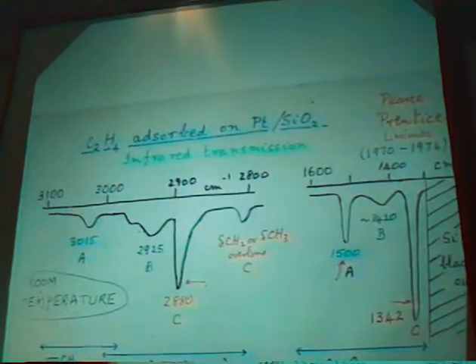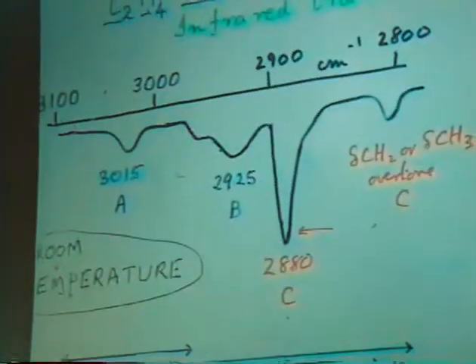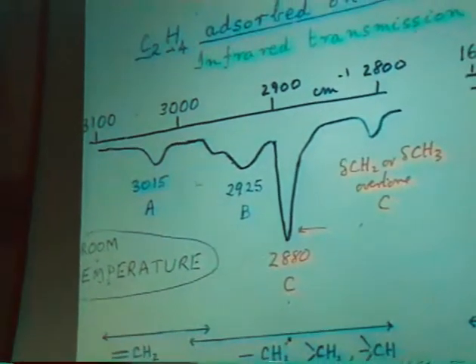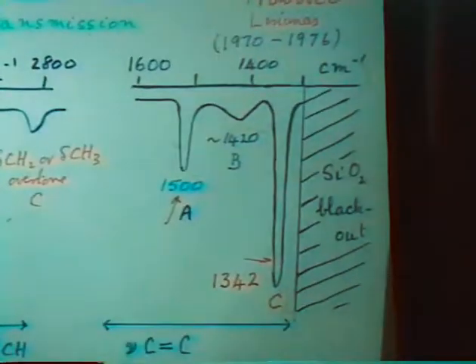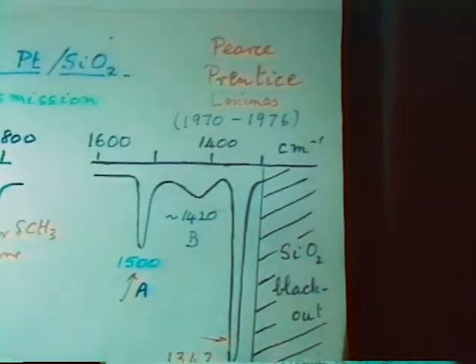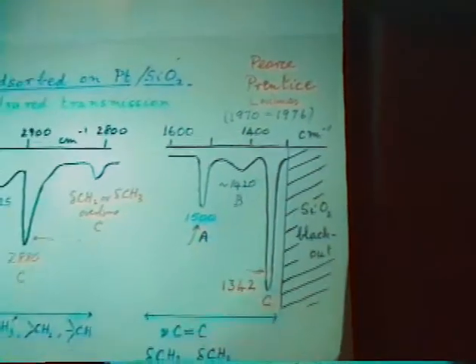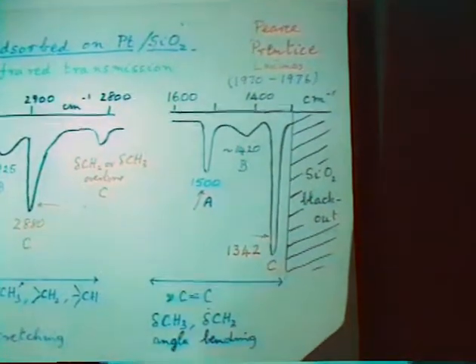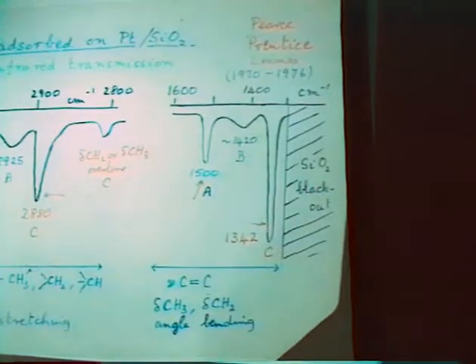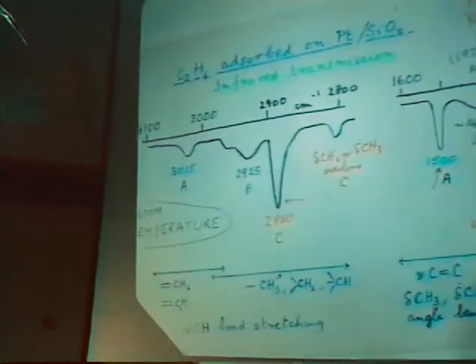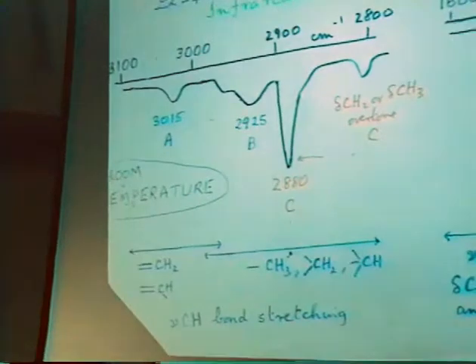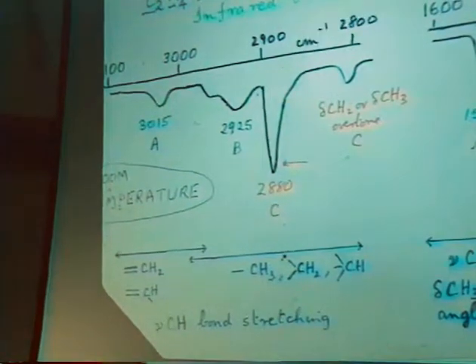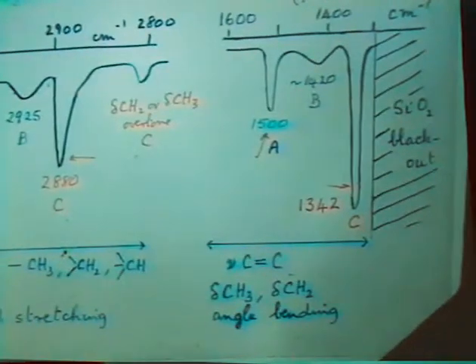And so when we did this, of course, we added another part to the spectrum. Here's what I showed you before, and these are the extra bands which we found at low wave numbers, down to 1300 wave numbers, where the silica blackout means you can't measure anything anymore. Well, what I have done is actually to label the high wave number and the low wave number bands according to species without knowing what the species are. But that is already a simplification. As a matter of fact, for a long time, we thought that the strongest band in this part of the spectrum and the strongest band in this part of the spectrum were from different species.